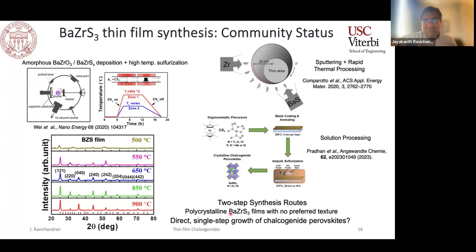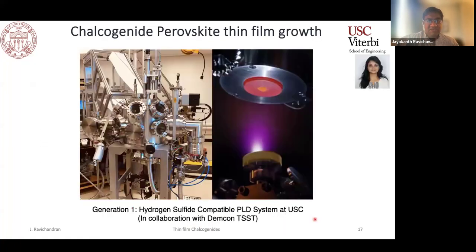So one of the early questions that we had is, can you grow direct single-step thin films of these chalcogenide perovskites? This is why we built the first generation hydrogen sulfide compatible PLD system at USC. This work started around 2018 or so, and my student Maitreyi worked closely on designing and building this system in the beginning. Once we had set up some of these systems with relatively corrosion resistant parts to ensure that these systems don't break down all the time, because typical PLD systems that you buy are much more compatible with oxides, but not necessarily corrosive systems such as sulfides.